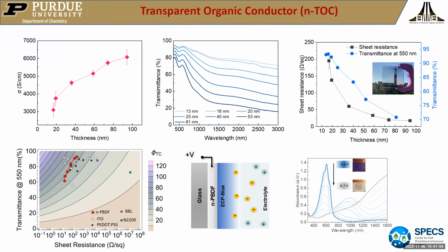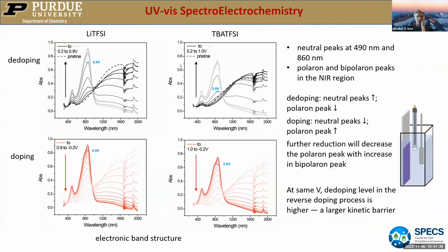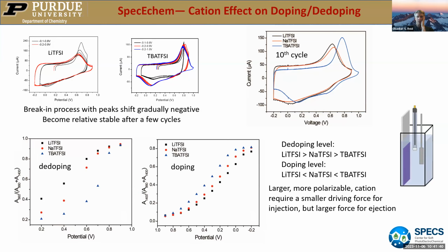Obadiah, did you have a question? I did. Neil asked the first part of it, which was, what's the counter ion, and are you expelling it, or essentially exchanging it? But I did want to follow up on that a little bit. I find it interesting that you do have some trends in the de-doping depending on the cation. But if you're starting out with protons in there, you would think that when you de-dope it, you're either expelling the cations that you have, or intercalating new anions to help compensate them. And so I would expect the correlation to be with changing the anion, not the cation in the solution.